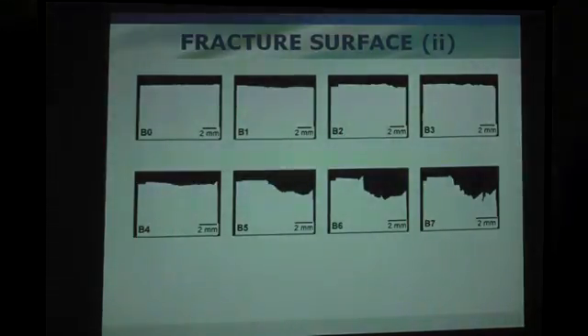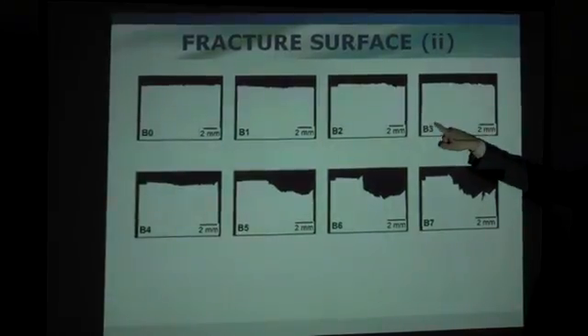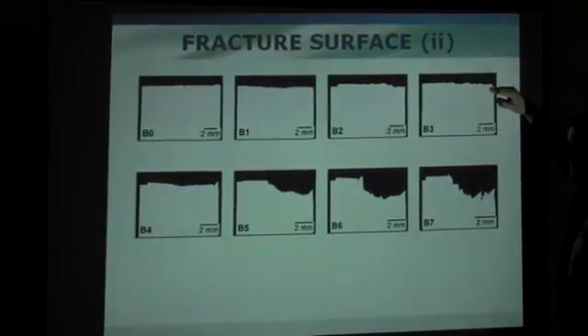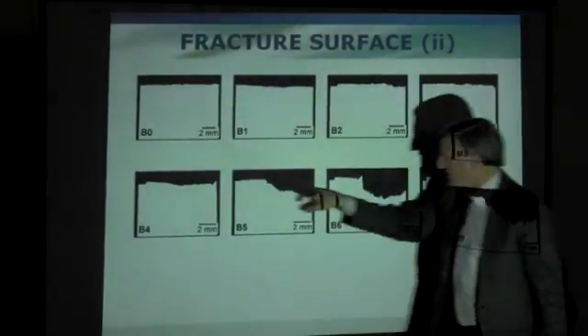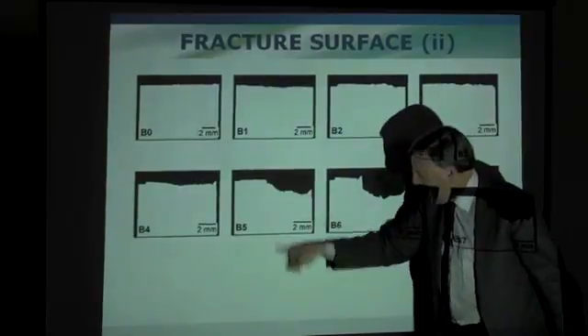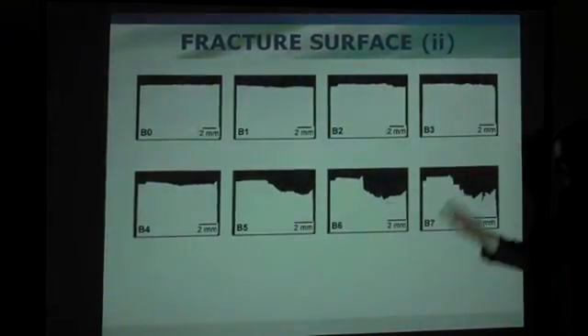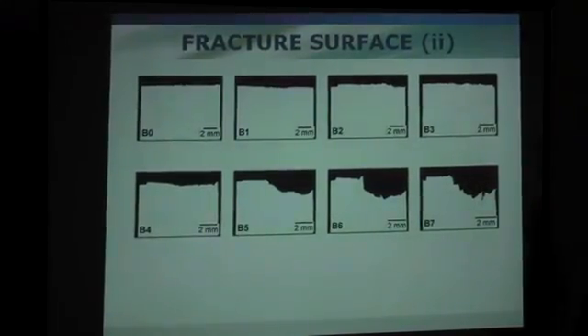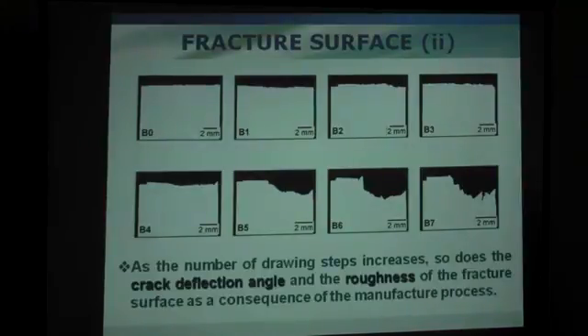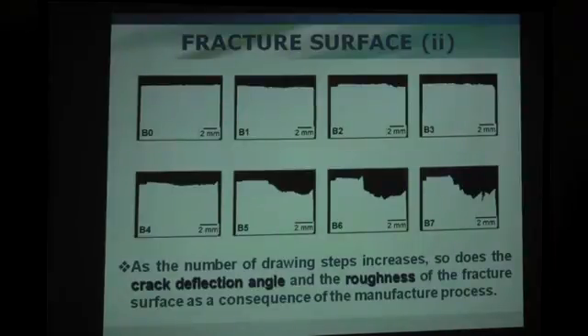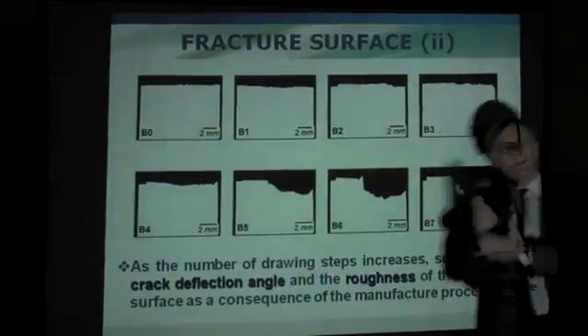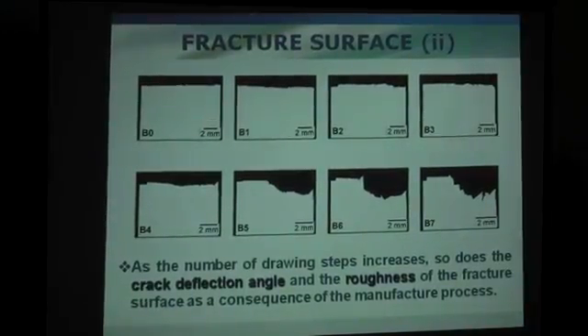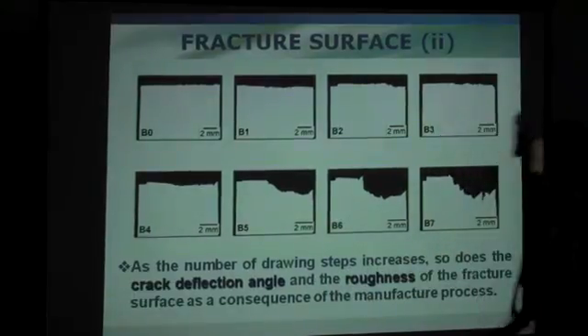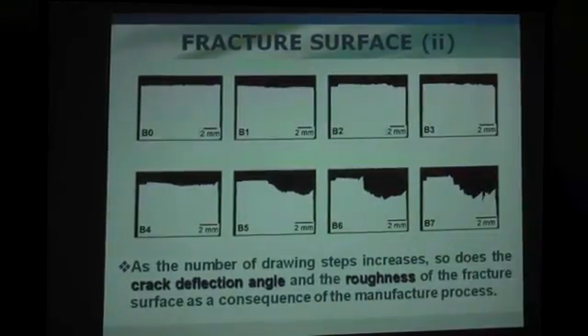Here we have the profiles: quasi-isotropic behavior up to step 3 of drawing with an increase of roughness, and the anisotropic deflection effect appears from B4, 4 steps of drawing, clear in B5, more pronounced in B6, and very marked in B7, with a very stepped fracture surface and a crack deflection angle, the microscopic angle, reaching almost 90 degrees, quasi-parallel to the drawing direction or y-axis. As the number of drawing steps increases, so does the crack deflection angle. We spoke about the microscopic angle in the previous slides, and the roughness of the fracture surface as a consequence of the manufacturing process.